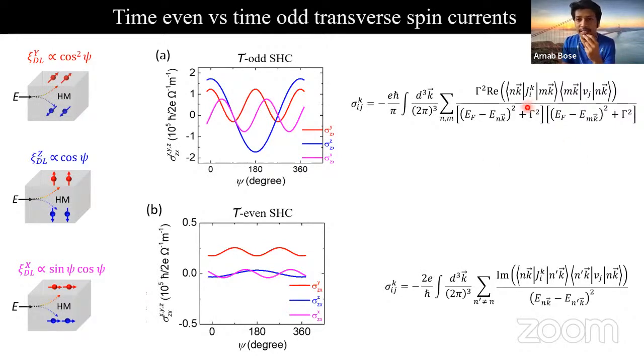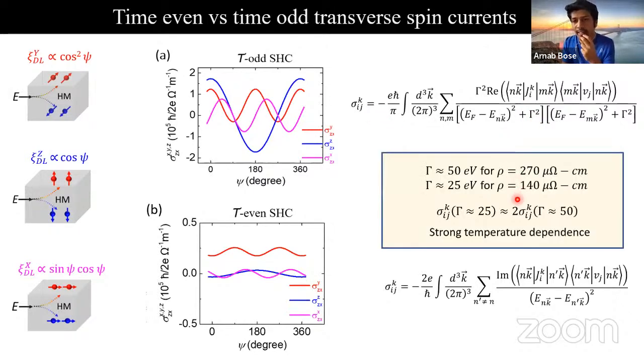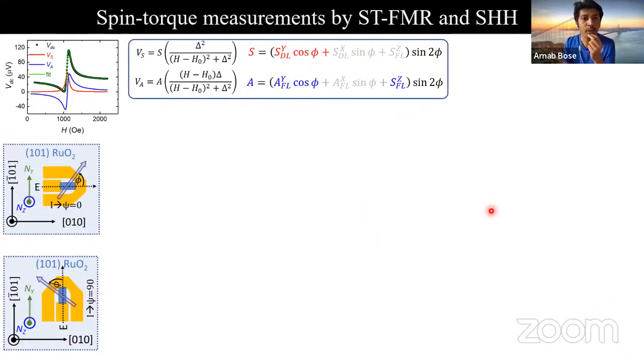And second thing is that in the expression, there is a scattering parameter for the time odd spin current. And we find that if we change resistivity by a factor of 2, then that will result in a strong change in the spin Hall conductivity. So this is something which we can also experimentally try to observe. Okay. So now let's move on to the experimental part.